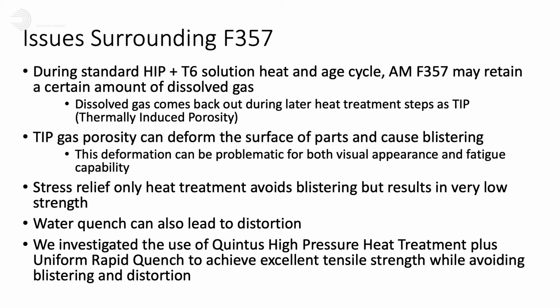First, it's an alloy that's from the casting industry originally. And so a lot of the heat treatment practices have been designed for cast parts, typically some larger structural castings. So the common practice for heat treating it involves a solution heat treatment and then a water quench as part of the T6 temper. This water quenching process can cause issues like distortion, that can be especially pronounced in thin, near-net shape additively manufactured parts.